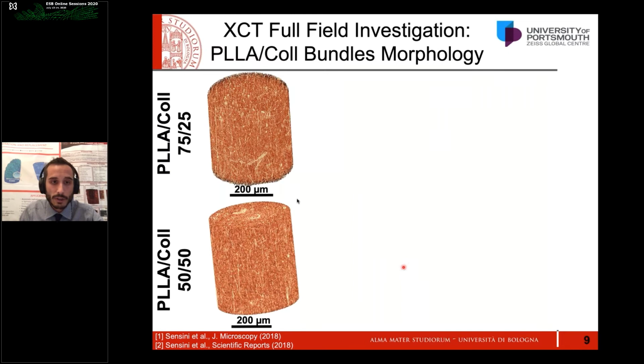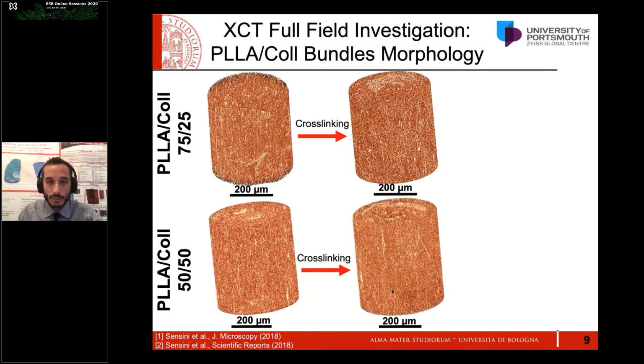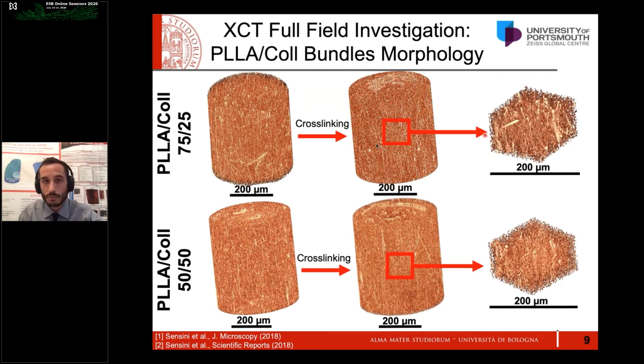Here are some results of our XCT scans for the two PLLA and collagen blend bundles. You can see that the nanofibers are well defined and preferentially aligned, both on the surface and in the internal volume of the bundles. After the cross-linking process, the nanofibers maintain their preferential axial alignment and their shape and structure, also in the most internal volume of our bundles.